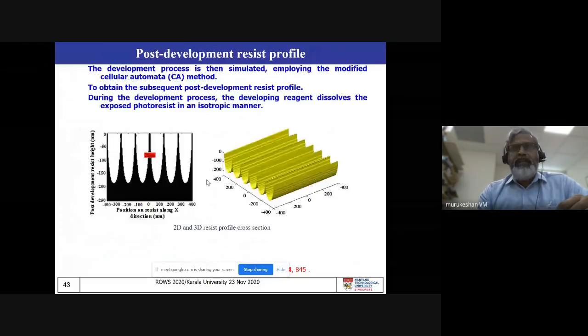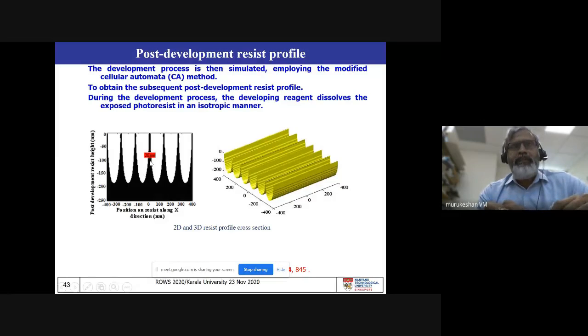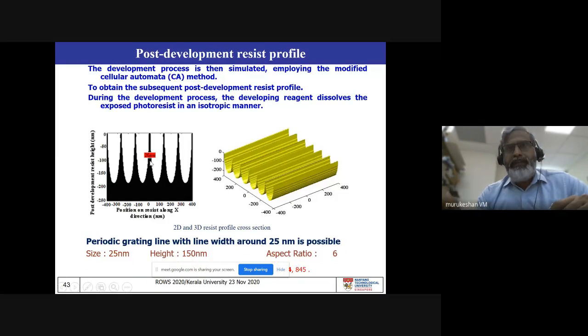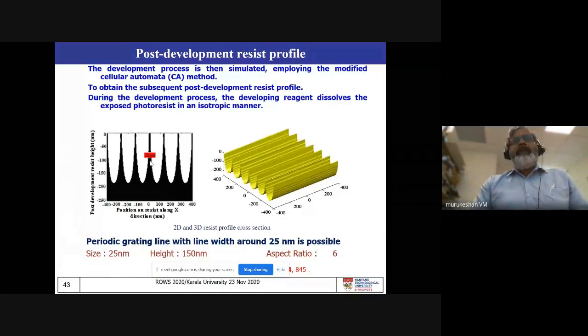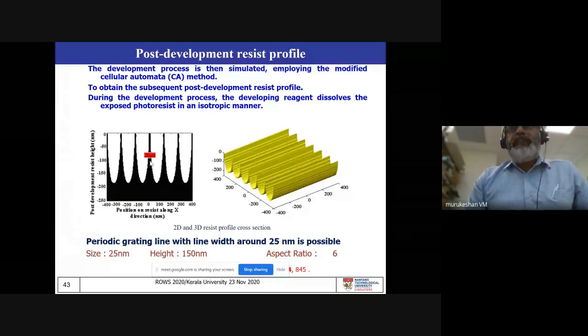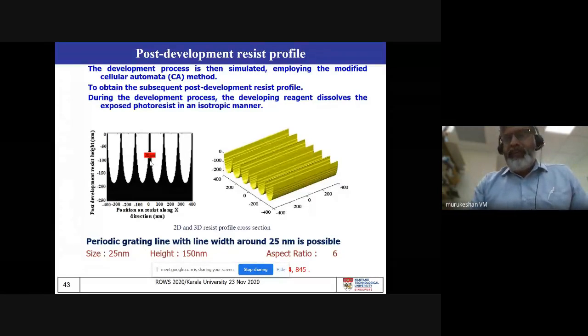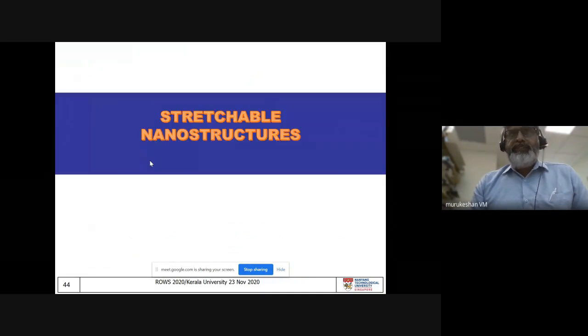What it means is that it is going to give a very good penetration in the z-axis, very good enhancement in the z-axis, and we are trying to do that, and we were able to get this data at about 25 nanometer with approximately not 8 but approximately 6 aspect ratio. And that is actually the work we have done as far as this interference based approach is concerned. So that is about the periodic structures.